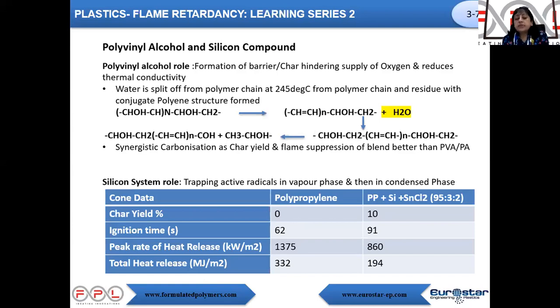Then we have the polyvinyl alcohols. Here also there is a formation of a barrier char which hinders the supply of oxygen and reduces the thermal conductivity. Water is split off from the polymer. So at around 245 degrees centigrade, it releases water. Almost all the systems which I have discussed release water. And here, if we consider polyvinyl alcohol and polyamides independently, there's hardly any char formation.